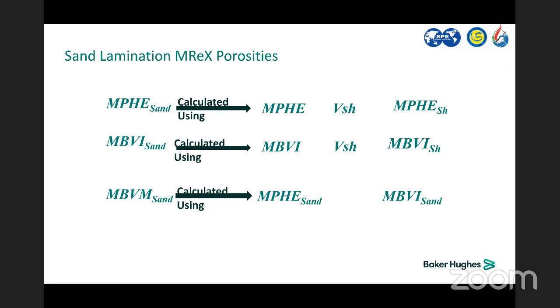Just to avoid confusion, NMR acquires based on the cutoff you provide to the service provider, and they will give you free fluids based on that cutoff. But the complaint we received, which is why we enhanced this workflow, is that while NMR is a good tool, sometimes it's not giving me the amount of free fluids. You can see the production is high, or the well test showed high permeability, while the NMR showed less free fluids and less permeability. What we applied here was to exclude the laminar volume of shale.